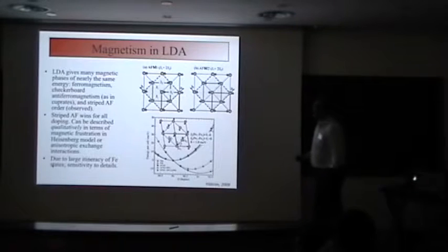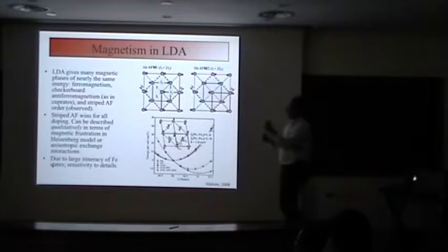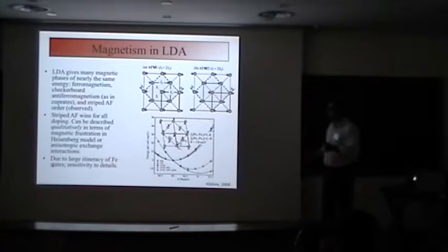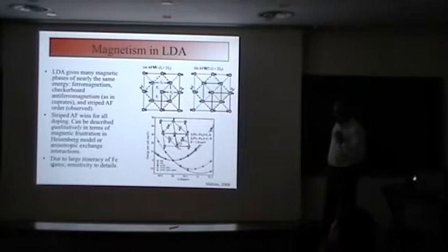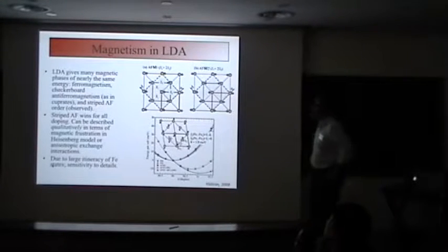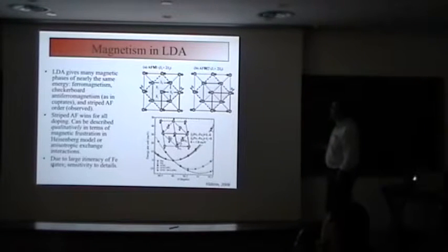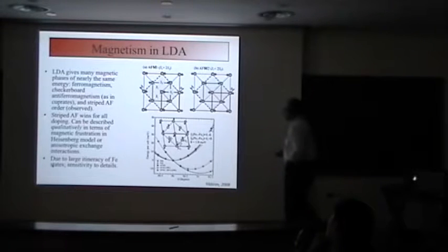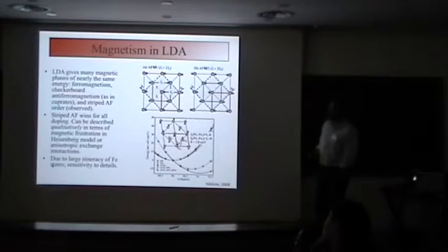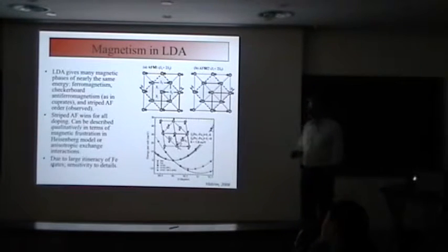Early on, LDA was combed to determine what the magnetic ground state would be, putting in a particular type of order and looking at the energy to find the lowest state. This included ferromagnetic states, checkerboard antiferromagnetism, or striped antiferromagnetic order. It turned out that for almost all studies, the striped antiferromagnet wins for all doping.